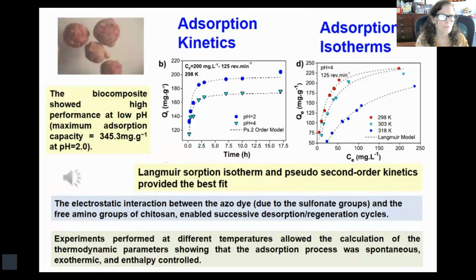Biocomposites show high performance at low pH. Langmuir sorption isotherm and pseudo second-order kinetics provided the best fit. The electrostatic interaction between the azo dye, due to the sulfonate groups, and the free amino groups of chitosan enables successive desorption-regeneration cycles. Experiments performed at different temperatures allow the calculation of the thermodynamic parameters, showing that the adsorption process was spontaneous, exothermic, and enthalpy controlled.